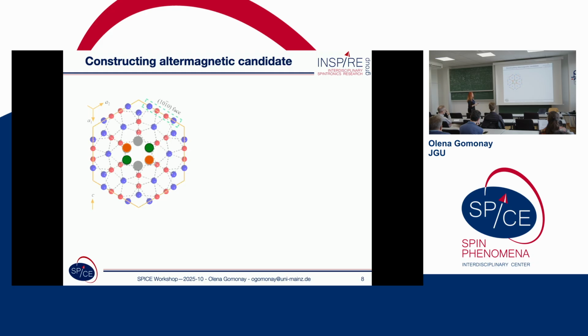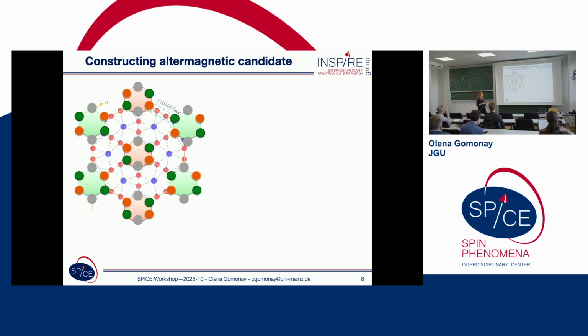But you can see that this kind of hexagonal structure can also be distributed within the lattice in different ways. And one way to order these hexagons is shown here. So you can see that along these lines we have chains of orange, orange, green, green, which means that this type of exchange interaction is antiferromagnetic, and this structure corresponds to the antiferromagnetic case. Though the material has a possibility to be a G-type altermagnet, it has proper local symmetry, it's not enough in the real case, because in the bulk material this ordering multiplies the unit cell 6 times, and then ends up in the antiferromagnetic structure.